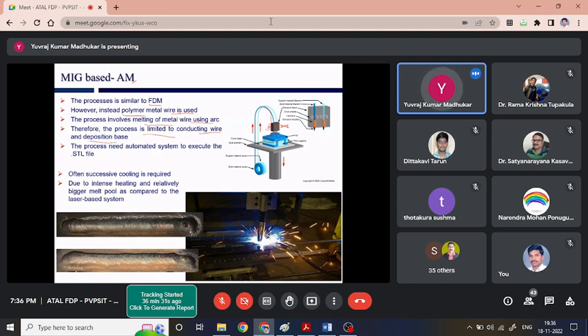The process needs an automated system to execute the .stl files. For that only we will make this CNC workstation. Often successive cooling is required due to intense heating and a relatively bigger melt pool as compared to laser-based systems. Yes, in a WAM process, whether it is WAM MIG, WAM TIG or WAM plasma, the melt pool size we are typically dealing with is relatively higher. So successive cooling after the deposition of each layer is often required.